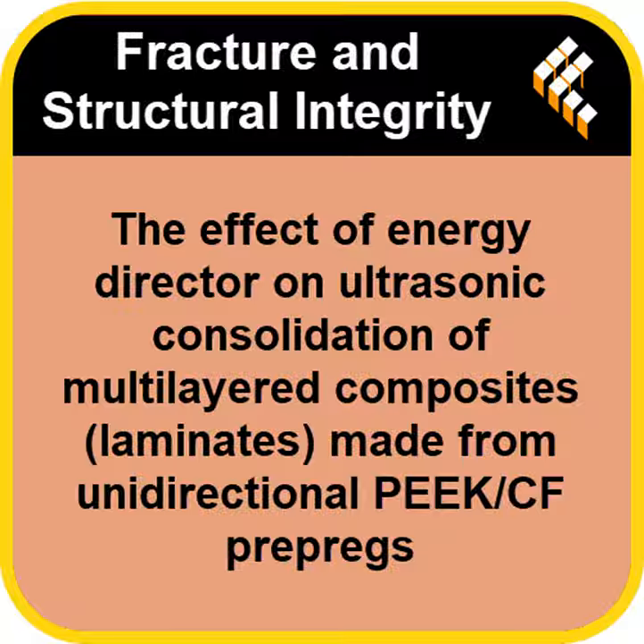So you were getting a strong joint, but you were weakening the composite overall. You were masking damage with a high strength number. Exactly. The real aha moment isn't finding the highest number, it's finding the most rational choice. And that was? The most rational defect mitigating choice was 800 milliseconds without the energy director.